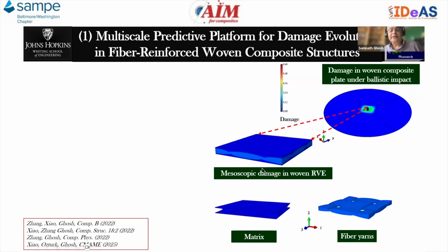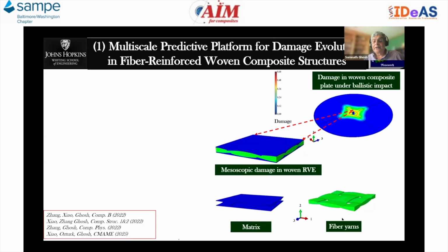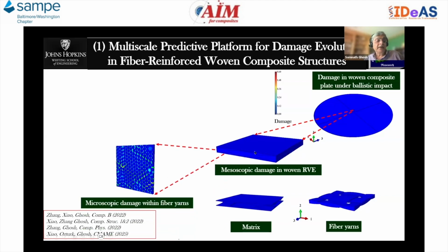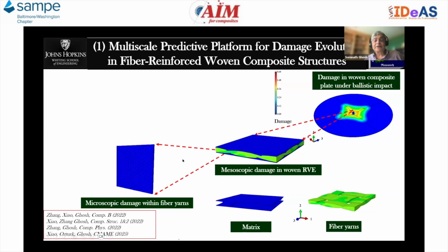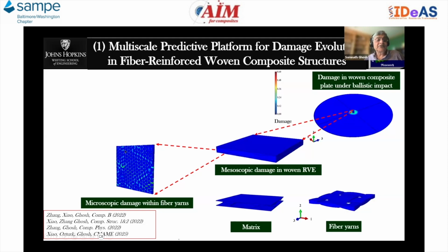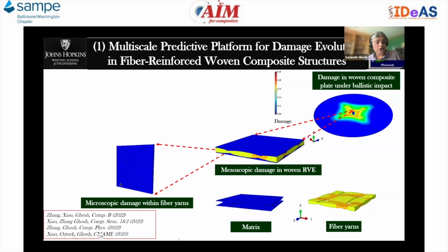In the mesoscale, this corresponds to the evolution of mesoscopic damage in the woven RVE. And if I look further down, I see the matrix with matrix damage, and then there are these fiber yarns. If I look inside of these yarns, I see this fiber matrix composite microstructure, and the damage starts through mechanisms of matrix cracking, interfacial debonding and such at this scale. So the link between these scales is very important, because one needs to connect the lower scale damage and failure phenomena to the failure phenomena happening at the higher scales.